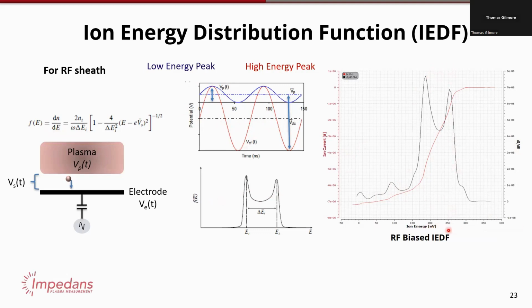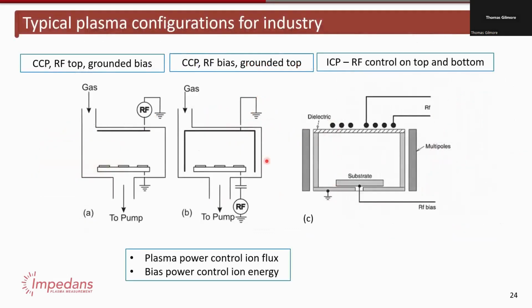So you see much higher energies, going up to say 300 eV. You have peak splitting, and then you also have these additional peaks down here, which are to do with charge exchange collisions in the sheath. So how do we then separate out ion energy and ion flux? I mentioned that changing the tool configuration is an easy way.